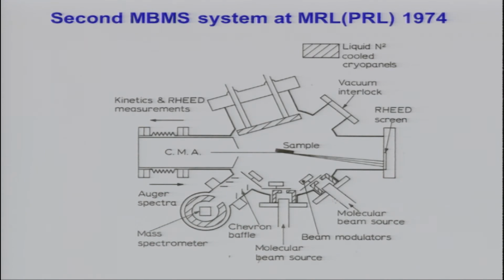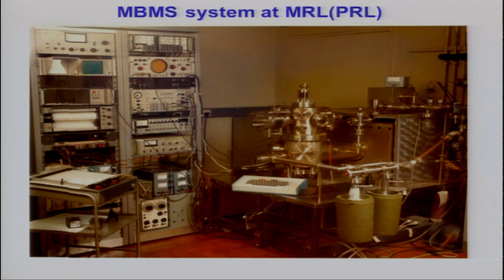Shortly after that, this system was modified because of the work that was going on at both Bell and IBM. In fact, we used the electron gun from the Auger system cylindrical mirror analyzer here to provide a RHEED pattern on the surface, and introduced a vacuum interlock, even at that very early stage. But other than that, it was essentially the same system. Okay, what did it look like? A bit of a mess, really.